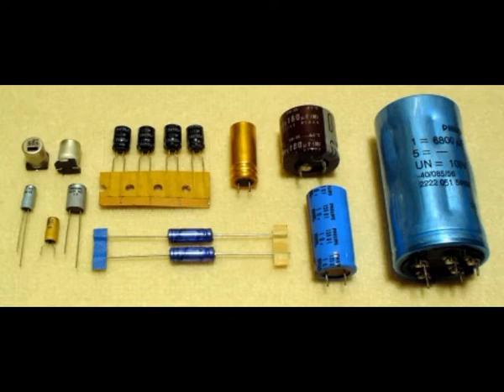The rated ripple current of aluminum electrolytic capacitors with non-solid electrolyte corresponds with the specified lifetime of the capacitor series. This current may flow permanently over the capacitor up to the maximum temperature during the specified or calculated time. Ripple current lower than specified or forced cooling lengthen the capacitor's lifetime. The lifetime of electrolytic capacitors with non-solid electrolyte depends on the evaporation rate and therefore on the core temperature of the capacitor. With forced cooling or special positioning of the capacitor on the PCB, the lifetime can be influenced positively. The ripple current is specified as an effective RMS value at 100 or 120 Hz or at 10 kHz at upper category temperature.